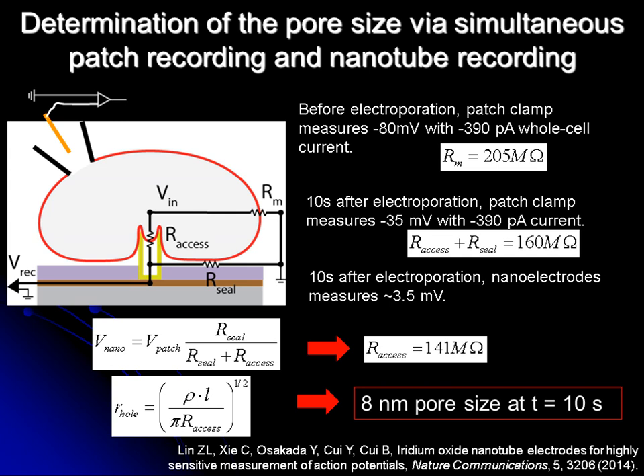So by using the constant current patch, we can measure the membrane resistance before electroporation and also measure the membrane resistance after electroporation. Through the equations shown here, I will skip the meaning, we can experimentally measure the size of the nanopore that we created through electroporation. So we measure the size to be around 8 nanometers, 10 seconds after electroporation.